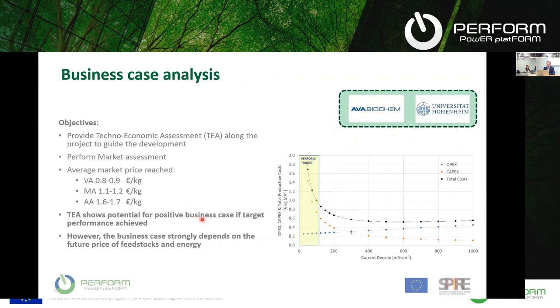And you can look at the sensitivity analysis in the graph. This is the current density, so that's the number of electrons that you could put in your electrolyzer per surface area. And this is the OPEX and CAPEX. I think this is the total levelized cost in this case of maleic acid. You can see that if you increase the current density with the same order of magnitude, so the same size of reactor and equipment, your costs go down.